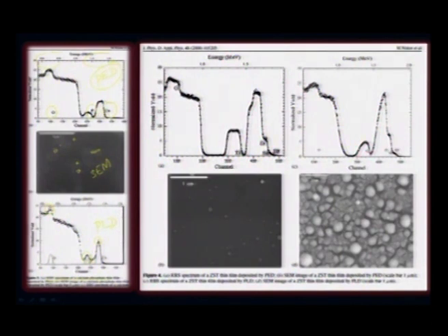And similarly, if you look at zirconium tin titanate ZST, the RBS spectrum is given for both PED deposited and PLD deposited film. As you can see here, in this case there is some problem with the oxygen stoichiometry here, but titanium and zirconium seems to be doing pretty well. And if you look at the PED, oxygen stoichiometry is actually guaranteed. There is no problem here.